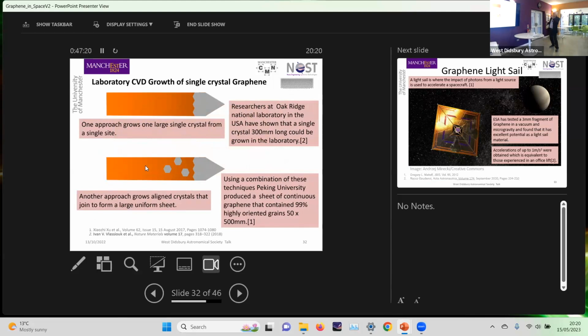And let's taper the end of the copper so that there's a point where a crystal will start growing first. And that crystal will grow large, and the others will adjust the conditions so they don't grow, they're suppressed. And then you can make a single crystal. And in fact, in Oak Ridge, they've made a single crystal piece of graphene, which is 300 millimeters long. About a foot, okay, not too bad.